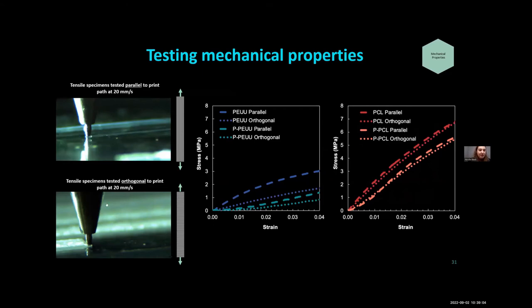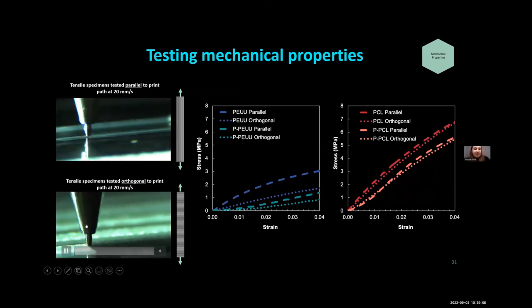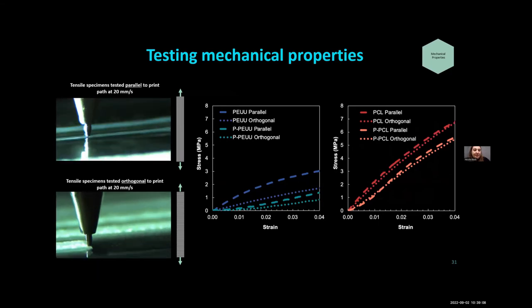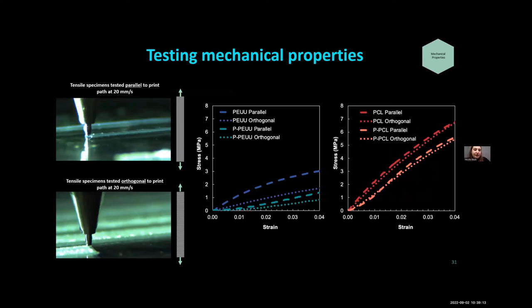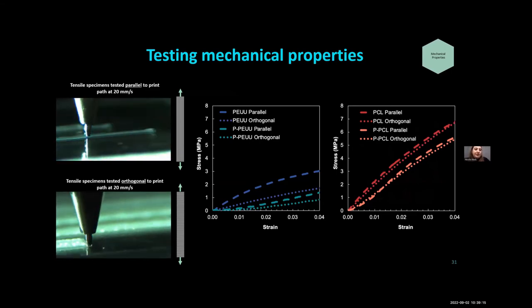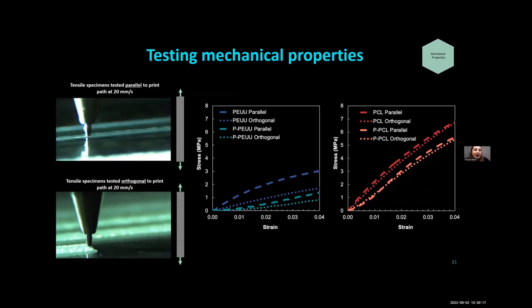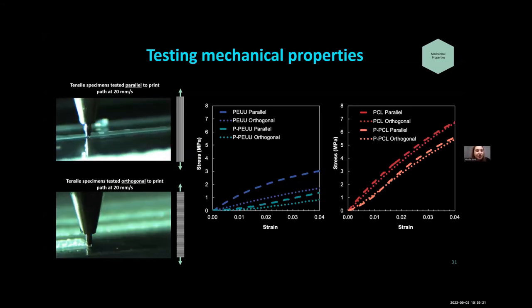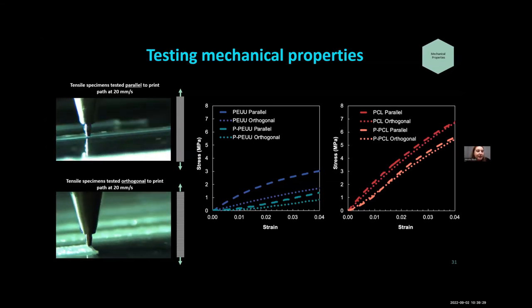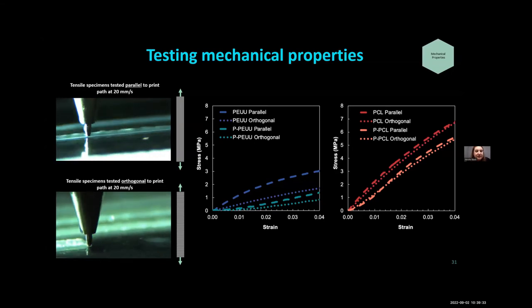And so one thing that we wanted to be able to do was to encourage these materials to be stiffer, essentially parallel to the print path, rather than perpendicular. And so we hypothesized that by applying these very high shear stresses in the nozzle, we could achieve something similar in terms of mechanical anisotropy. So we printed these dog bone specimens for tensile testing, either parallel to the print path or perpendicular. And then you can test out the relative stiffness of them.